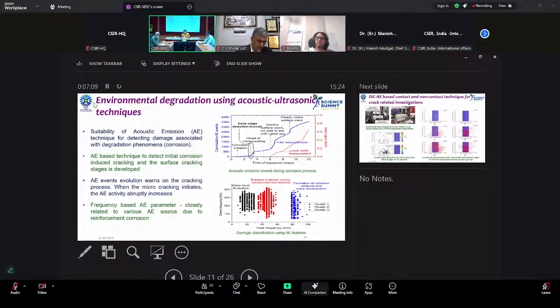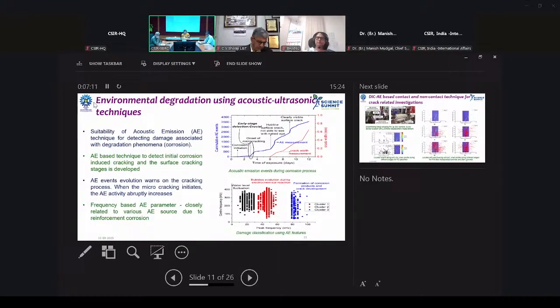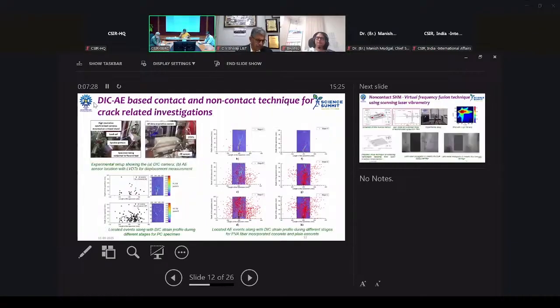you get the fusion of the data, because the acoustic emission and the ultrasonic show, if you see in the graph, that when the micro crack starts in the vicinity of the reinforcement, where the actual crack on the structure is far away, that type of early warning system can be developed, and it can also be deployed to nearby structures.